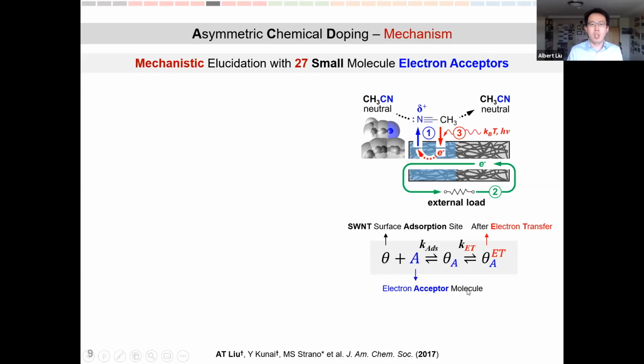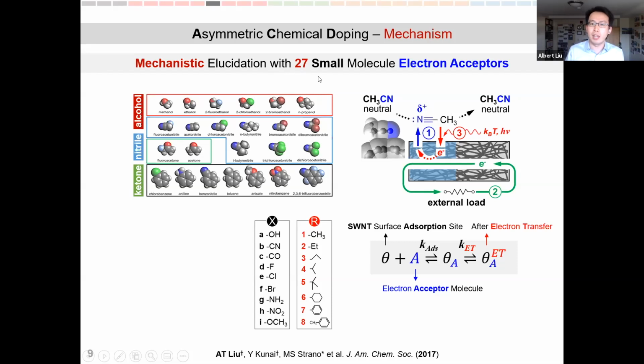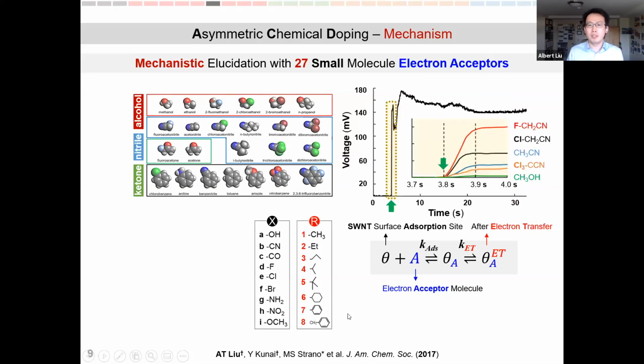To answer that question, we tested 27 other small organic molecules for overall electron transfer rate. In these organic solvents, we're varying in between alcohol, nitrile, and ketone, changing its functional group to tune its electronic structure and electron withdrawing power, and also its steric hindrance for tuning molecular size. The experiment is very simple. What we're doing is we measure the voltage output of all 27 small organic molecules that are electronic acceptors, and we check its initial voltage ramp-up rate. So this dV/dt, the slope, differentiates all of these molecules from each other.